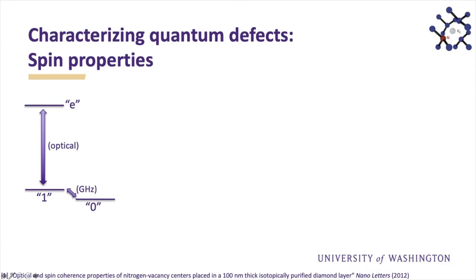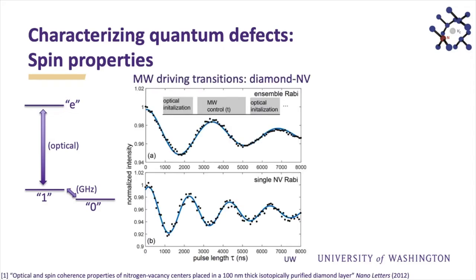All right, so once you've done this spectroscopy, you now have determined what these levels are. And now we have to know is it going to be a good qubit or not? And so the first thing that we want to do is understand or create a superposition state, create a qubit state. We're not interested in just having zero or just having one, because those are just classical states. And the way you do that is you have a coherent resonant field. So in this case, you're applying a radio frequency field to this transition. In diamond, in the NV center, it's about 3 gigahertz. And you can coherently drive this population, and you can see that it's coherent because, depending on the pulse length, you see the population oscillate back and forth as a sinusoid.